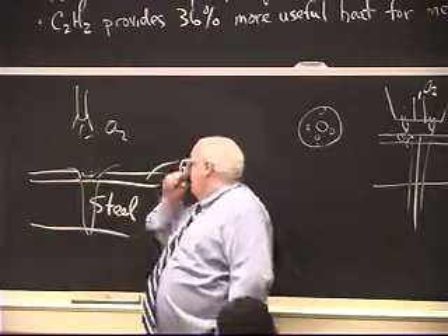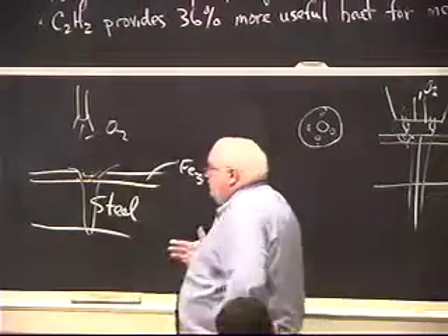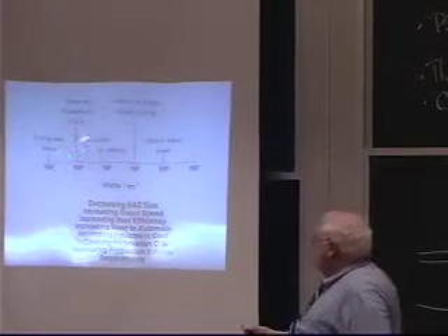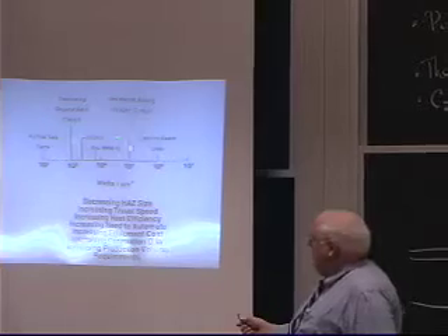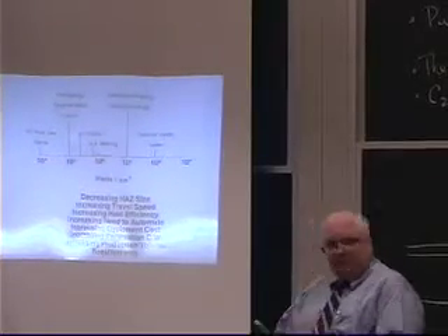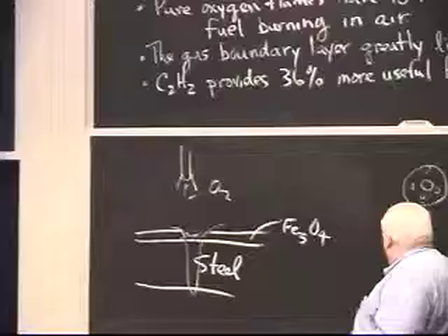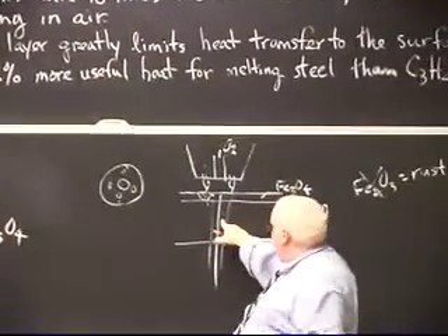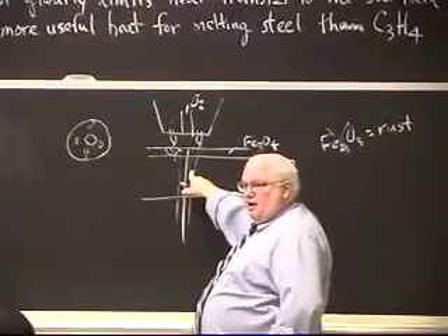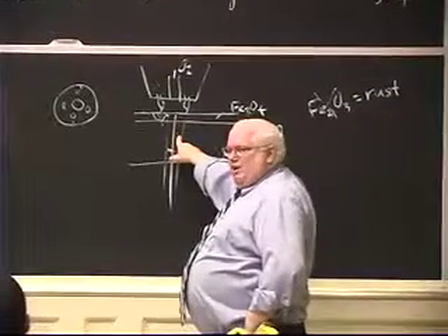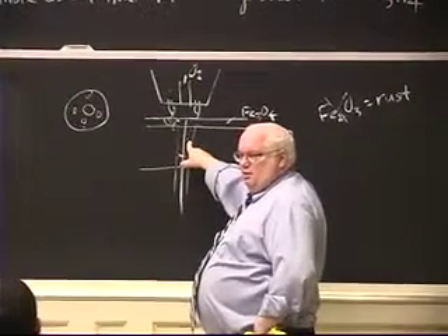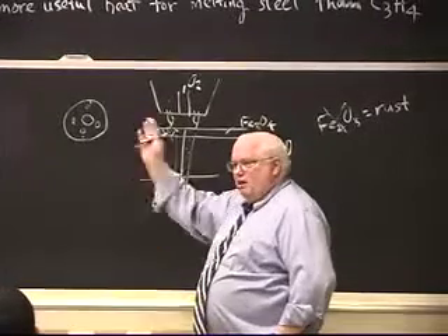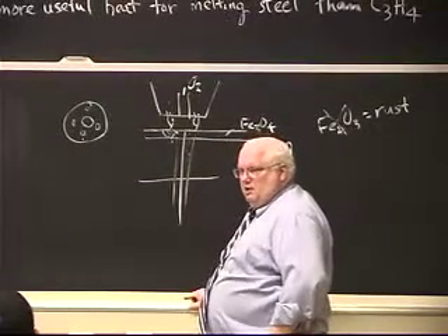Okay? I'm burning it to iron oxide, and if it's now nearly 100% efficient, if I go from 2% efficient to 100% efficient, I get almost 2 orders of magnitude. And if I calculate the relative melting efficiency over this little area and do my mass balance and everything, I will get heat transfer efficiencies in burning equivalent to about 100,000 watts per square centimeter. More intense than a carbon arc, than an arc weld. I can blow metal out of there faster than I can arc weld when I'm oxyacetylene cutting.